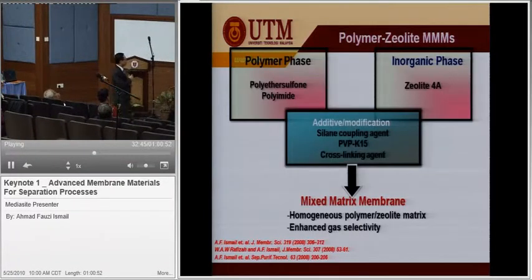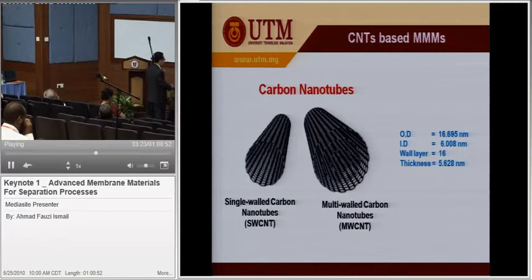Another one is polymer-zeolite. The outcome of this marriage between polymer and zeolite is a homogeneous polymer and zeolite matrix which enhances gas selectivity. So we do this and we published some selected publications, quite recent ones. So in order to reduce the defect just now, we add a silane agent as a cross-linking agent.